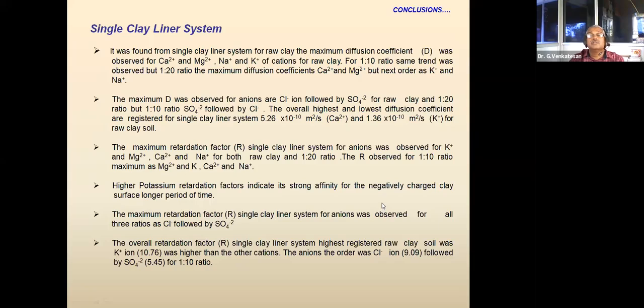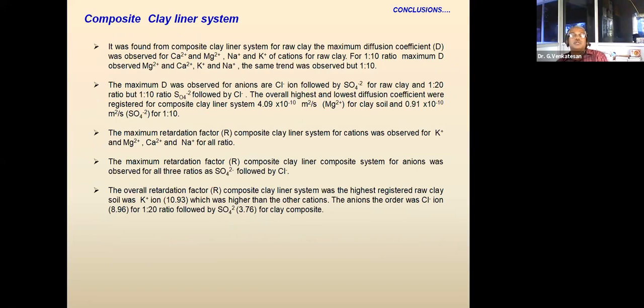Based on the single clay liner system and the double clay liner system, the maximum diffusion coefficient was observed for calcium and magnesium and the other elements. Among anions, chloride had the maximum diffusion coefficient. The maximum retardation factor in the single clay liner system was observed for the anion, and a higher retardation factor was observed for potassium. Similarly, in the composite clay liner system, maximum diffusion coefficients were observed. The maximum retardation factor of the composite clay liner system among cations was observed for potassium and magnesium.